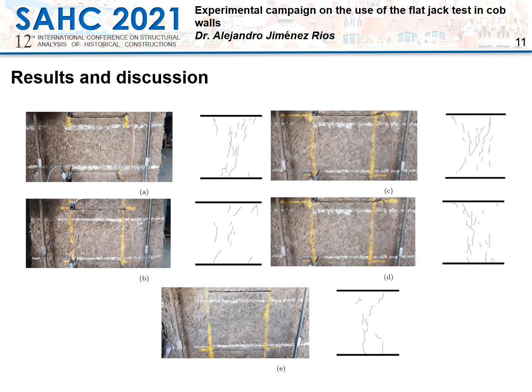Regarding the failure patterns observed after the completion of the double flat jack test, a consistent pattern was identified in the form of a series of vertical cracks, mainly concentrated at the center of the material between the two horizontal flat jacks. This set of vertical cracks is more similar to the typical vertical crack pattern that appears in compression tests under point load, such as the Brazilian test, than to the typical X-crack pattern characteristic of a simple compression test. This agrees with the assumption that the non-uniform deformation of the flat jack transmits a load more similar to a point load than to a uniformly distributed load to the material.